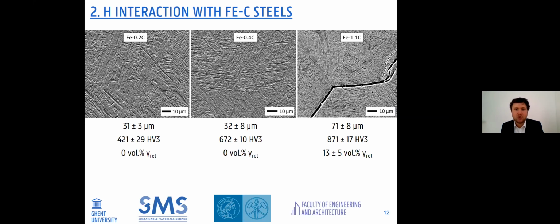Quench cracks appear due to thermal stresses in the steel when the carbon content is larger than 0.7 weight percent. Since, of course, the appearance of plate martensite is required there. Next to that, also when the carbon content exceeds the eutectoid composition, you can have cementite along the austenitic grain boundaries upon hot rolling already, and this facilitates also cracking, as you can observe in the 1.1 microstructure. So there we have quench cracks. The hardness values are nicely in line, so we're increasing with carbon content.